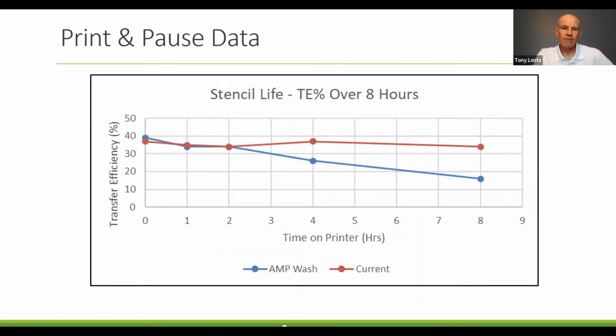Here's stencil life in a print and pause test over 8 hours. So we kind of combine stencil life and print and pause together in this one test. So you've got transfer efficiency through a 0.50 area ratio aperture. It's actually a 0.4 millimeter pitch BGA pattern that we're measuring here. And you can see the blue line is amp wash and the red line is the current technology paste.